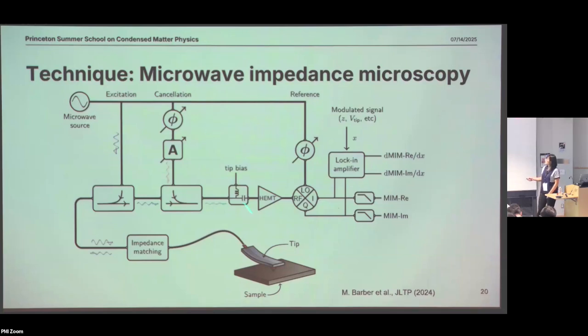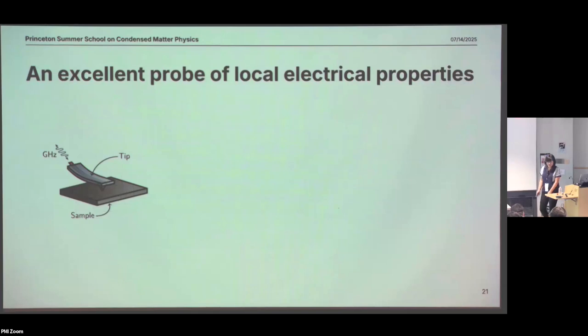So then there's also a cancellation circuit that is just for not having too much back reflective signal, not coming from the sample, but from elsewhere in the circuit, because having too much of that may jeopardize the gain of the amplifier, because it will get to its maximum too quickly. So because of that, we now have this whole circuit of sending a wave onto the tip and then measuring the reflection coming out of the tip with some amplification or gain, and going out to some measurement circuits.